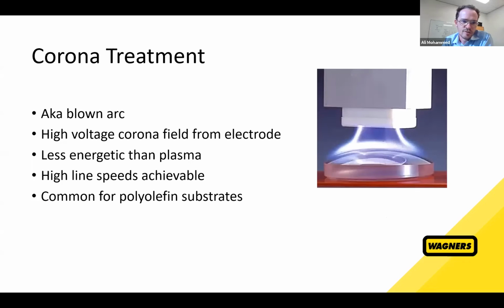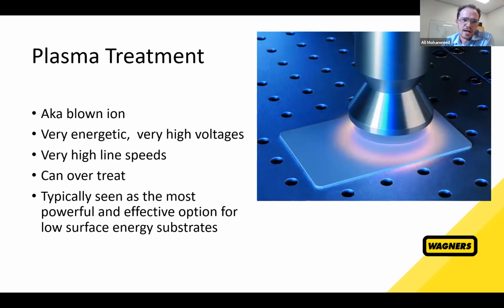The next one is corona treatment. It's whereby high voltage, high frequency current is passed through an electrode, and that generates a corona type field. On the right, you can see what it looks like. So it's a blue field, and you can use this to run over your low surface energy substrates and increase their surface energy. It's also known as blown arc, an industry term. It's quite good for high line speeds. So if you've got a continuous plastic processing operation or some operation that requires high throughput, it's quite good for that. It's very, very common for treating your polyolefin type plastics or your polypropylene, et cetera.